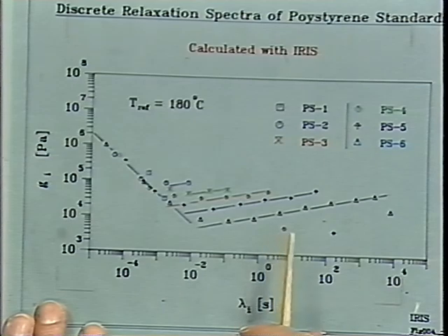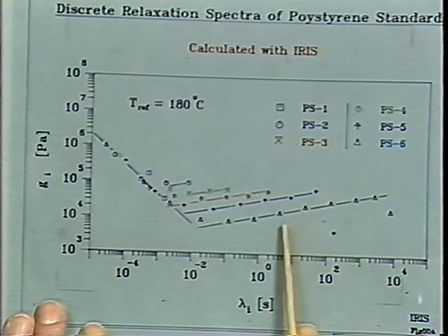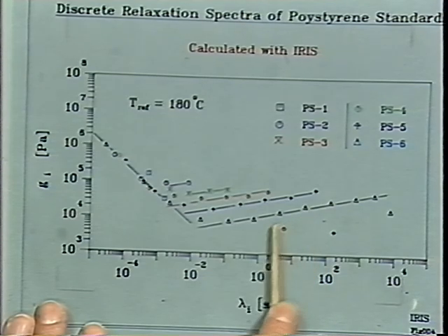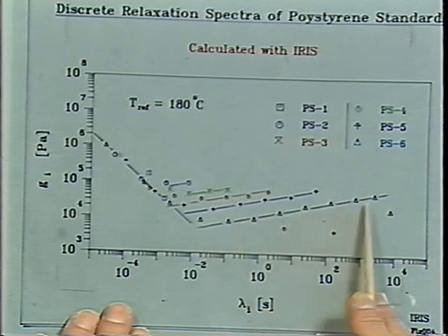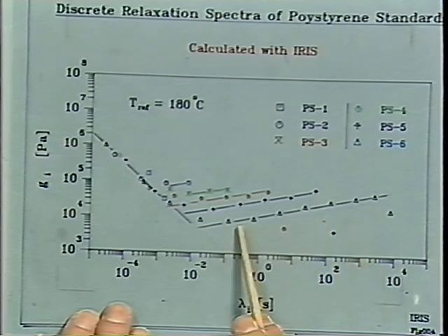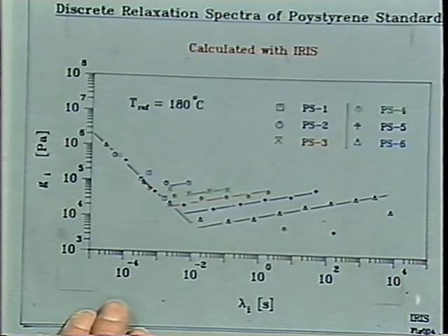Now, in our analysis, we didn't prescribe the spacing of those modes, and you can see they are at some odd positions, somewhere intermediate between the interval. But the material somehow chooses the modes to be most efficient in the fitting when they are spaced equally along that line and when they're sitting on the straight line. So there's a pattern in that spectrum.